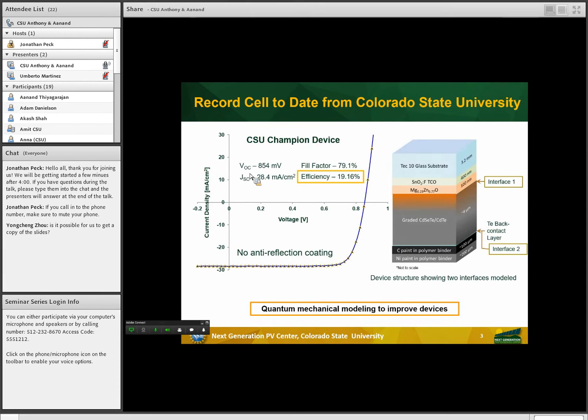Here at CSU, Colorado State University, we focus on CdTe-based thin-film solar cells, and we're steadily advancing toward more complex configurations to achieve higher performing devices. The Next Generation PV Center has recently achieved a record cell efficiency of 19.16%. As polycrystalline CdTe reaches higher efficiencies, quantum mechanical modeling is necessary for further device improvement. That's why we're using DFT to explore two interfaces of our current device configuration, as shown on the right. We're looking at both the MZO CdTe interface and the CdTe Tellurium interface. I'll be briefly speaking about the current progress on the CdTe Tellurium interface using DFT.